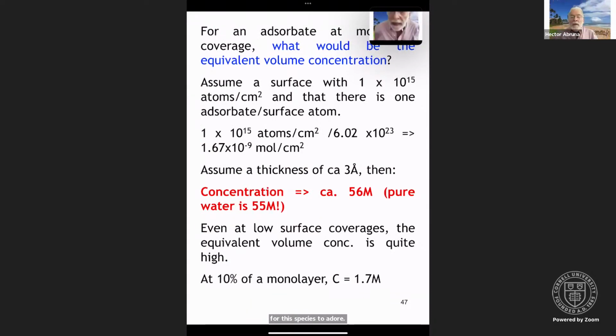It's interesting and revealing to consider surface coverage. What's the equivalent volume concentration of a surface at monolayer coverage? Let's assume a surface has 1 times 10 to the 15th atoms per square centimeter. That's typical of a metal surface, okay? And assume that you have one adsorbate per surface atom. So you have 1 times 10 to the 15th atoms per square centimeter, divided by Avogadro's number, and you have 1.67 nanomoles per square centimeter.